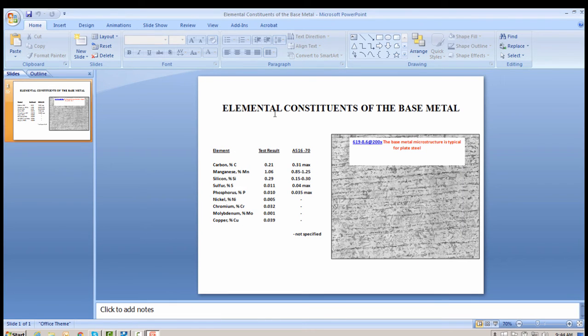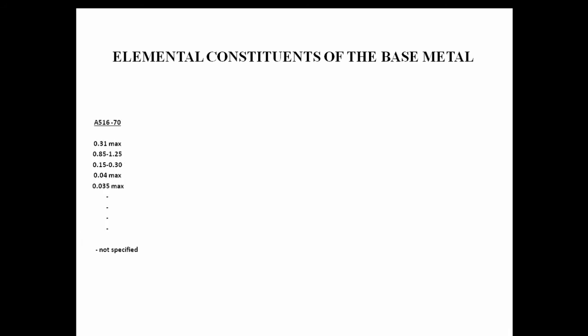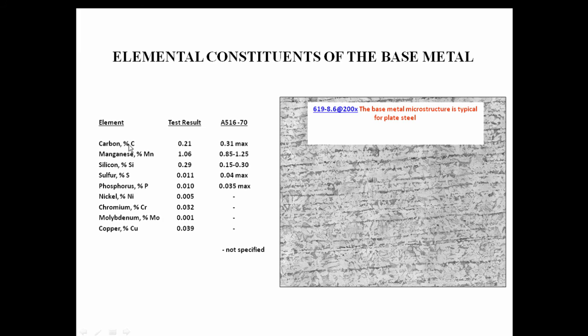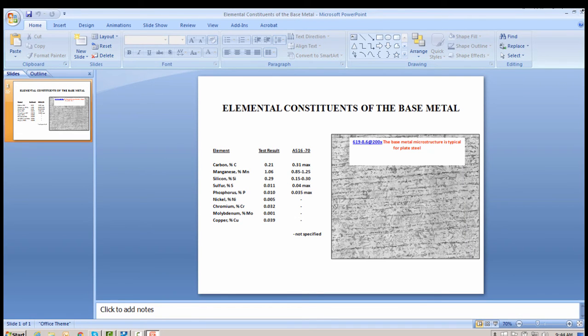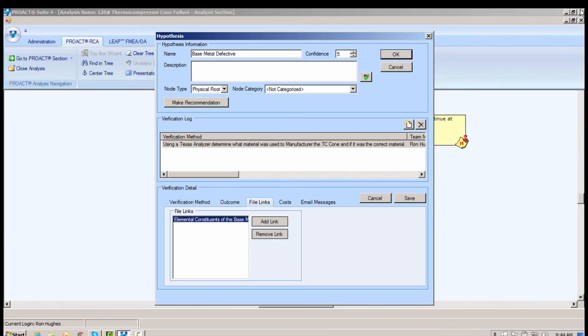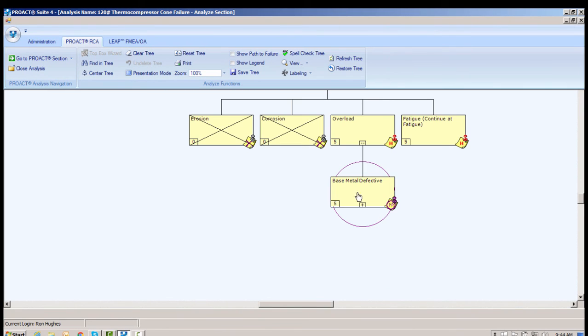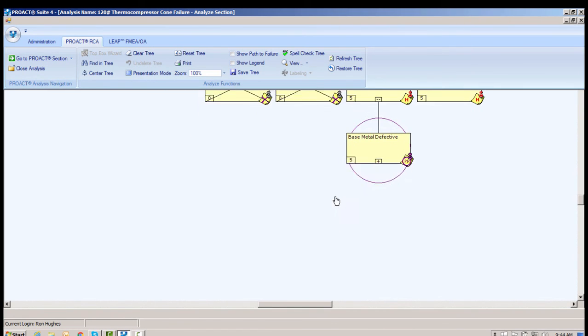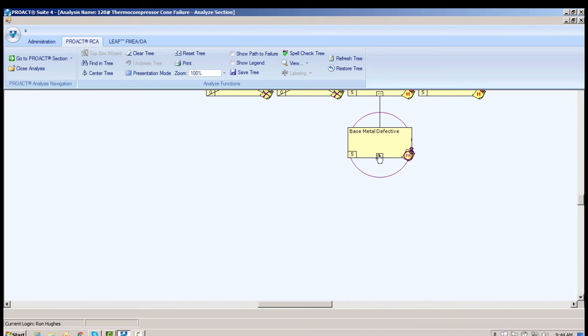And of course, here are the results of our analysis from the Texas Analyzer. These are our elemental constituents, and based upon the percentages, we find that this is definitely ASTM A516 grade 70 material. Okay, not the right material for the service. Base metal defective. How can that be?